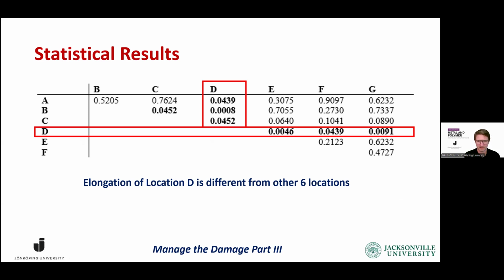And the idea with this test is to compare the average values in this case that we're looking at here. It's called a Mann-Whitney test, where you compare the distributions and see if they can be expected to be from the same distribution, or is there a statistically significant effect that they are from different distributions. So what we're looking at in the table here is the p-value that comes out from this test. And if that is below 0.05, then the distributions are different.